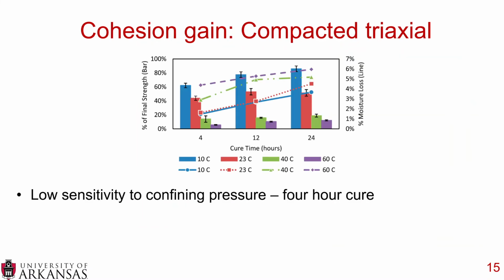Now looking at the cohesion gain for compacted triaxial, we found that there is low sensitivity to confining pressure, especially at the 4-hour cure. And this makes sense because these are fully compacted samples. We're not really expecting to see a whole lot of impact from the confining pressure.